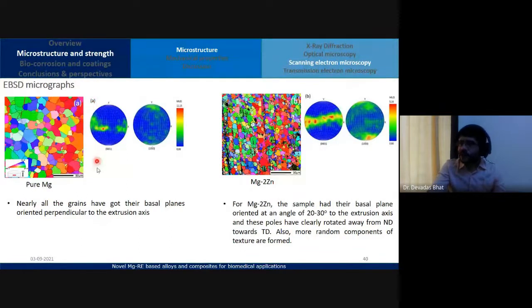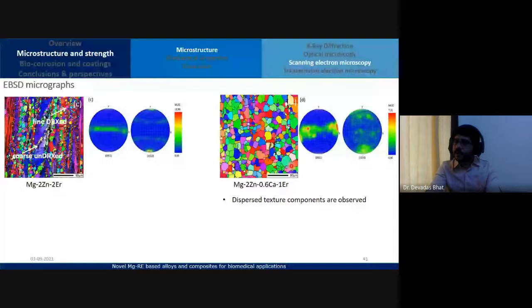So pure magnesium, you all know, has basal planes along the extrusion axis. Whereas if I add alloying elements, then I will see a small shift in the basal plane. It will be oriented at an angle to the extrusion axis. For the 2 zinc 2 erbium alloy, what we have seen is a prismatic component forming, and the basal texture is disappearing.